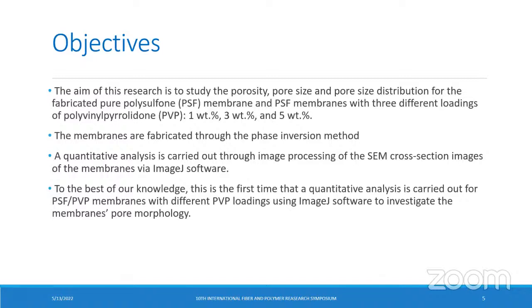The membranes in this research are fabricated through the phase inversion method, and a quantitative analysis is carried out through image processing of the SEM cross-section images of the membranes using ImageJ software. To the best of our knowledge, this is the first time that a quantitative analysis is carried out for polysulfone PVP membranes with different PVP loadings using ImageJ software to investigate the membrane's pore morphology.